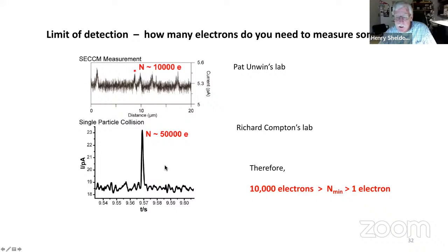And what's happening is the particle's hitting the surface, and when it hits, it gets oxidized, but then it diffuses away, and then it hits the surface again. And so you end up typically with about 10 peaks. If you resolve this with a faster time measurement, you'll get about 5 to 10 individual peaks here. And it's corresponding to the diffusion, random walk of the particle at the surface.